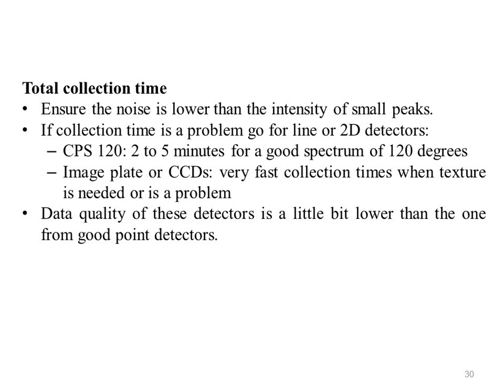CPS 120: 2 to 5 minutes for a good spectrum of 120 degrees. Good for quantitative analysis or following reactions and transformation analysis in temperature. Image plates or CCDs: very fast collection time when texture is needed or time is a problem. Data quality, not related to intensity, of these detectors is a little bit lower than the one from good point detectors, but sometimes intensity rules.